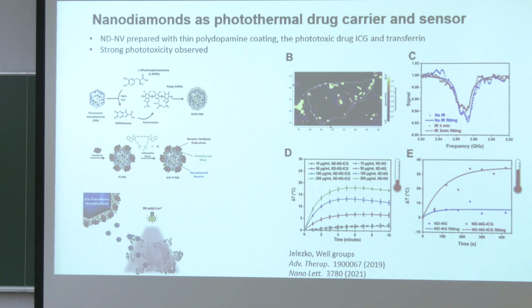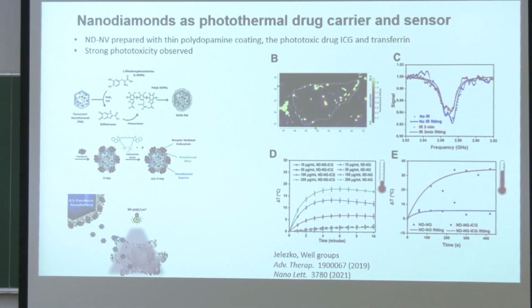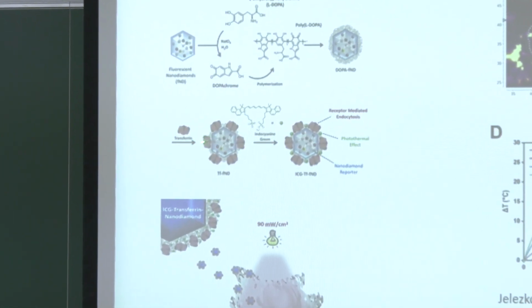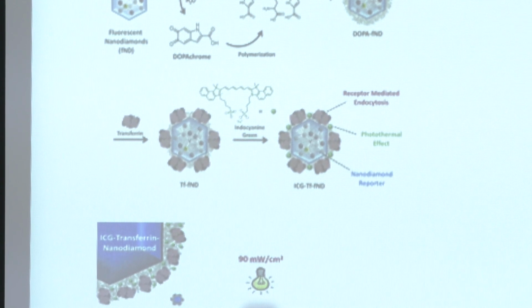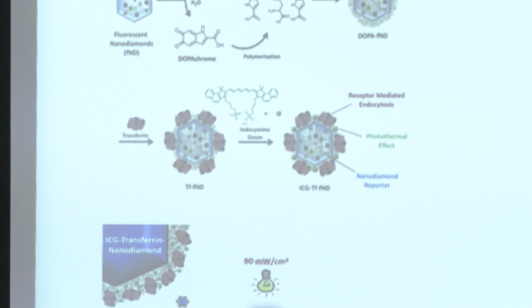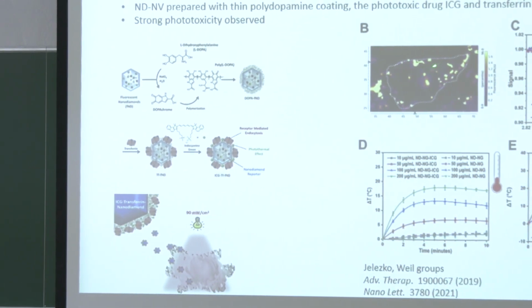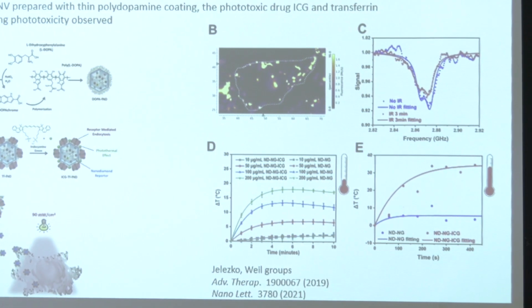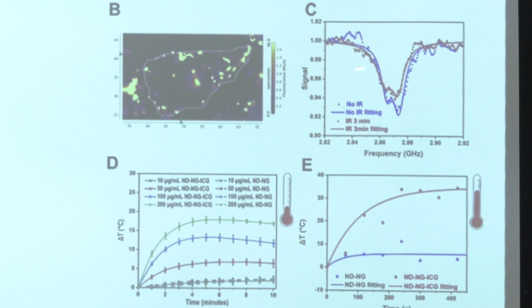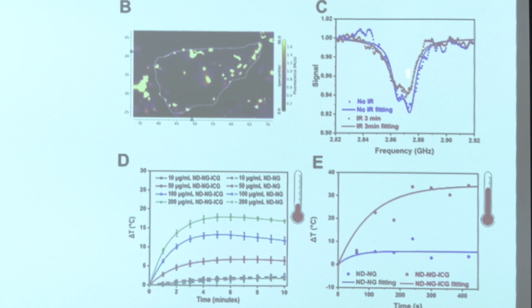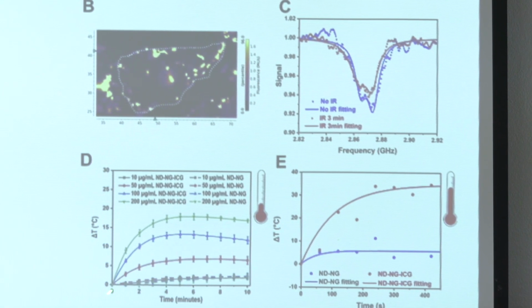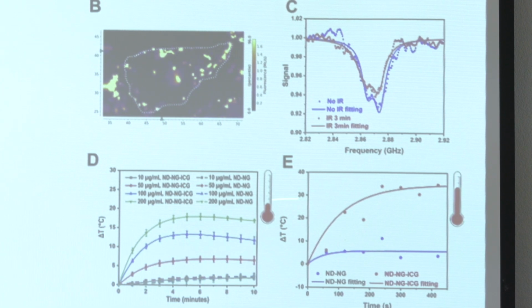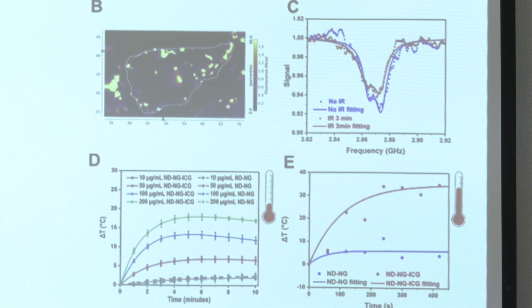In collaboration with Tanya Weil group in Mainz, we have been able to introduce cancer drug on the surface of nanodiamonds, and the release of the drug was triggered by temperature. There were also molecules that absorb the light, get hot, and lead to release of the drug. That were kind of on the surface of nanodiamonds, and then we have been able to illuminate the cell, having these nanodiamonds as a bright spot here visible, and then measure the temperature by measuring zero field splitting, by measuring these spectral features, it shifts depending on temperature, and measuring this temperature basically was correlated with release of the anti-cancer drug.